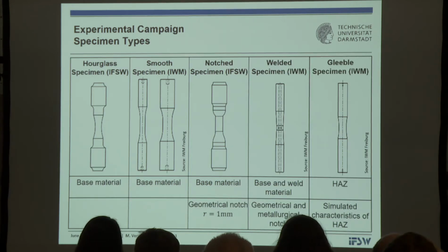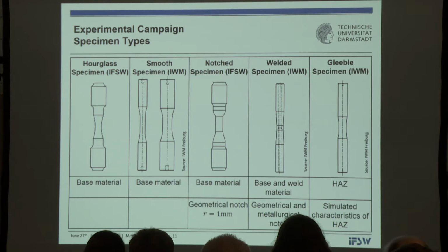So now I come back to our investigation of the current project I'm reporting on. These are the specimens which we tested: unnotched hourglass and smooth specimens, specimens with a notch, and even welded joints. And I have to appreciate the work of our co-workers at the Fraunhofer Institute on Material Mechanics in Freiburg, who did a lot of the experimental work and also own modeling, and they will report that on another occasion. And well, I also took their experimental results and performed calculations. Not I, Alexander Bosch did that.